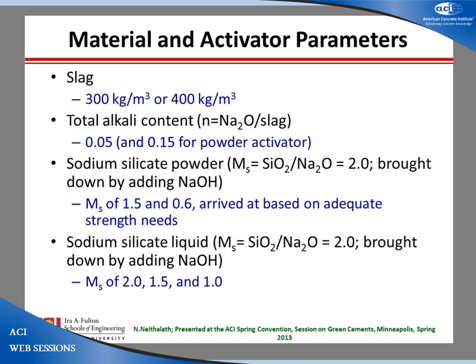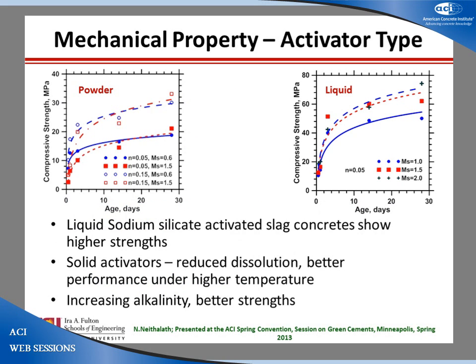So two different slag contents, total alkali content of 5%, and we did a higher one for powder too. Sodium silicate with a silica modulus of 2, and sodium hydroxide can be used to bring it down to 1.5. Sodium silicate liquid has silica modulus of 2, 1.5 and 1. So we did 3 different ones, but these two are the commonly used numbers. So, mechanical properties: if you look at compressive strength, your powder activated mixes will give you only about 30 megapascal. With liquids, you can go to 80 megapascals or even higher depending on the type of slag. But the reason is that with solid activators, you have a reduction in the dissolution. The compromise you are getting is for a system that you can work with very quickly without the need to store liquid separately somewhere else.